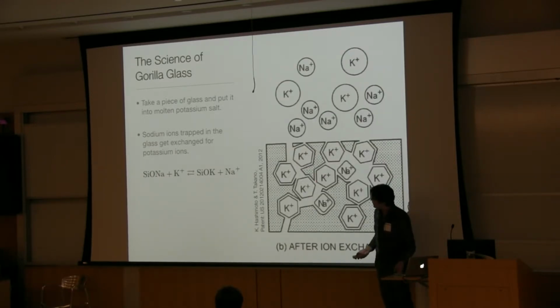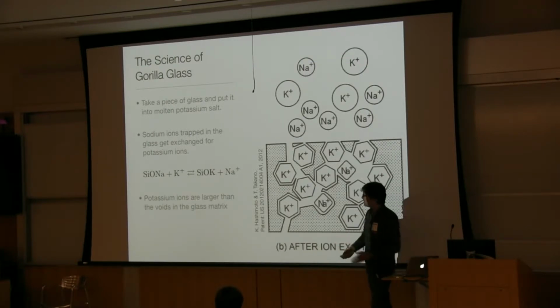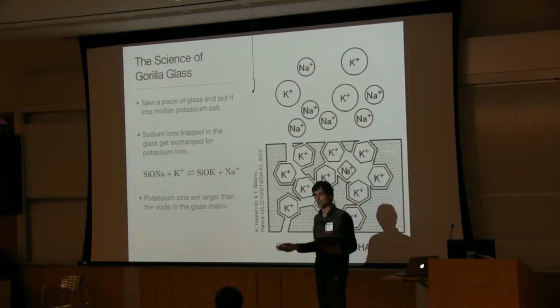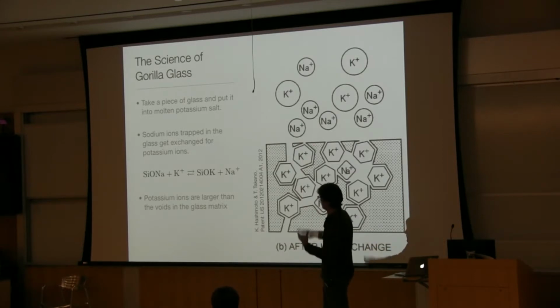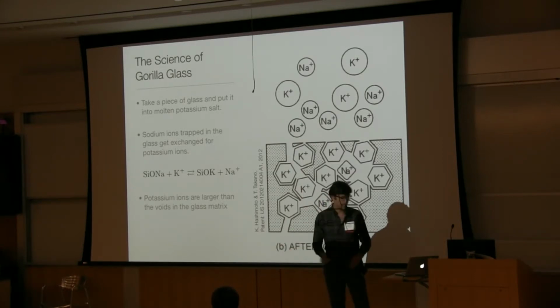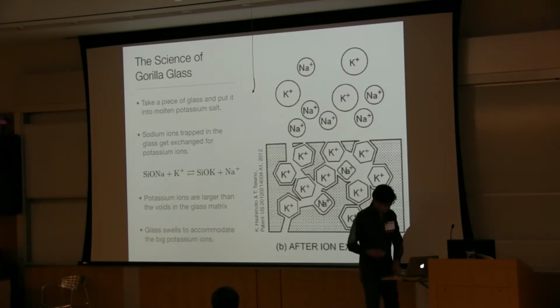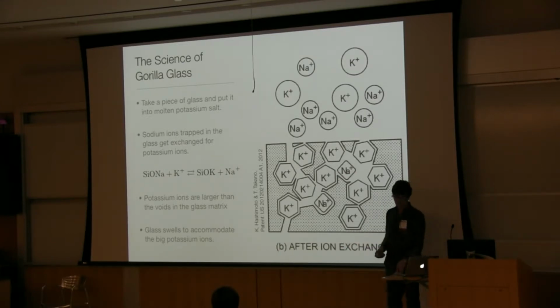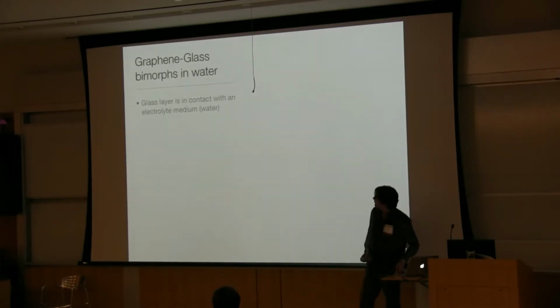That's all well and good, but there's a catch here, and that's that potassium ions are larger than sodium by a significant amount. And so once they've exchanged, they start to swell the glass, and that leads to stress inside of the layer. In short, the glass swells to accommodate the larger potassium. So okay, that's how Gorilla Glass works. What does that have to do with the graphene glass bimorph?